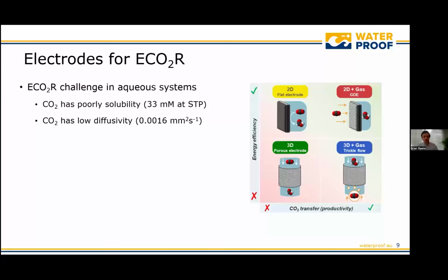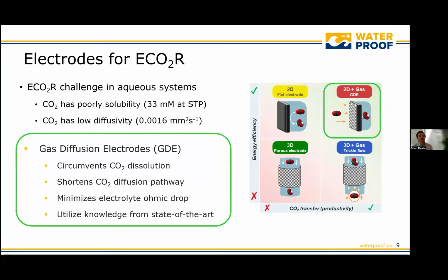So which electrodes do we use for CO2 reduction? There's a challenge when you're doing gas electrochemistry, that you have poor solubility in aqueous systems and you have quite a low diffusivity. So therefore your mass transport is poor. And that's why at Volta, we choose to go for gas diffusion electrodes, because they circumvent this issue of mass transport.